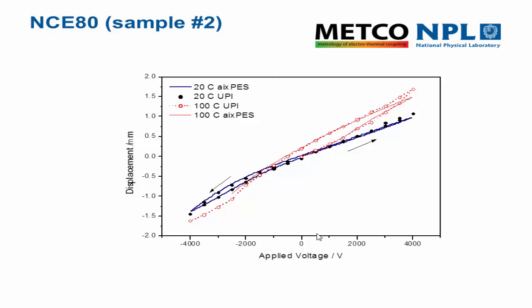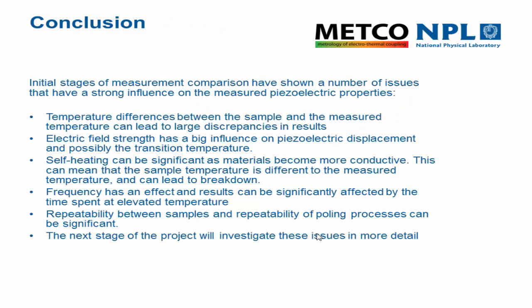And just to show the correspondence when that's been taken into account, for different measurement cycles but under comparable conditions, the blue line is the aixACCT result, the dots are the PTB results, and at room temperature they correspond very nicely, and at 100 degrees C they still correspond very nicely. As Guido said earlier, some of these results at the bottom end were where the sample was failing, so we can't read too much into those. But arranging the measurement cycles, the time of measurement, the time at temperature is all important for getting comparable results.